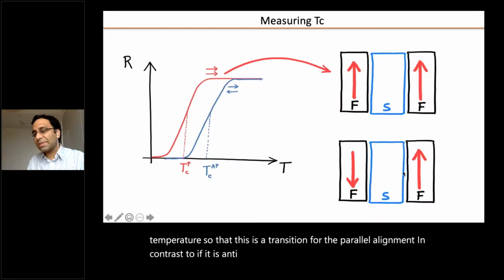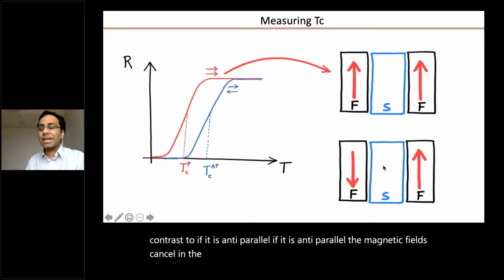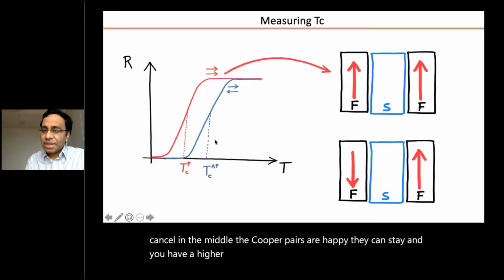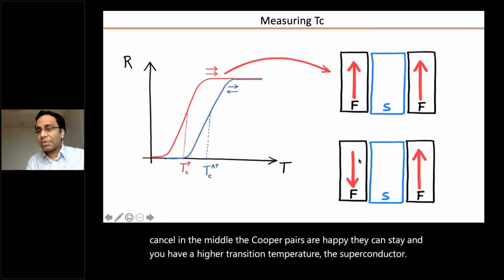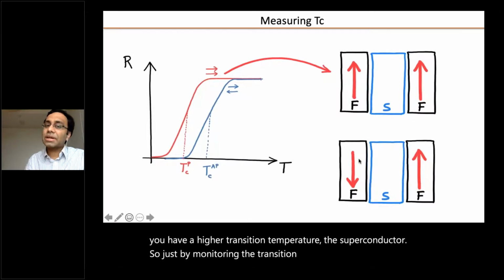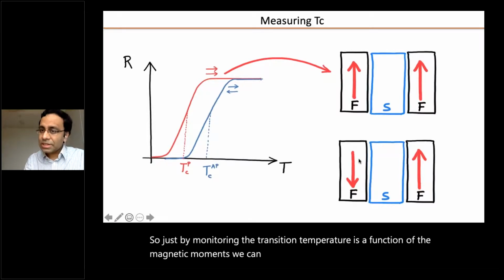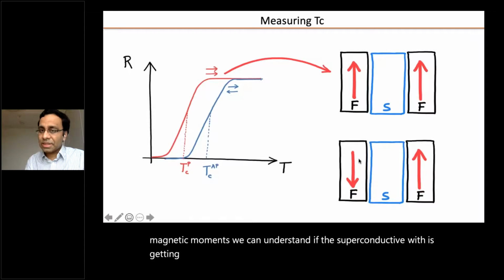in contrast to if it is anti-parallel. If it is anti-parallel, the magnetic fields cancel in the middle, the Cooper pairs are happy, they can stay, and you have a higher transition temperature of the superconductor. So just by monitoring the transition temperature as a function of the magnetic moments, we can understand if the superconductivity is getting weakened or is getting stronger.